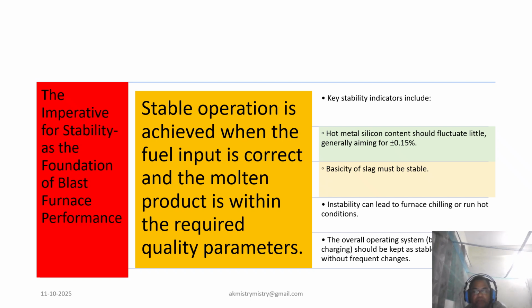Now, exceptional process stability is absolutely mandatory for maintaining high efficiency. A stable operation is defined by the correct fuel input and consistent product quality. The stability of operation is visibly reflected in the product chemistry. Crucially, the hot metal silicon content should fluctuate only minimally, with fluctuation generally controlled to within plus minus 0.15%, and this figure can sensitize us to what sort of fluctuation is desired.